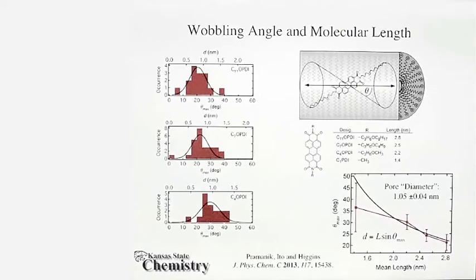This value is, of course, much smaller than the 3.7 nanometer diameter expected from the silica nanochannels themselves. This discrepancy arises from nanostructuring within the surfactant filled mesopores.